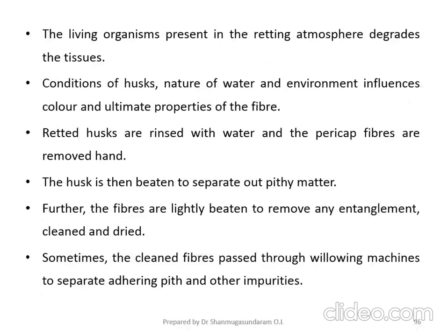So the living organisms present in the retting atmosphere degrade the tissues. The conditions of the husk, the nature of the water and the environment influence the color and ultimate property of the fiber. So during the retting process, you have to keep in mind the nature of the water and the environment, which will influence the color and ultimate property of the fiber. The water should be clean. If you use polluted water for the retting process, ultimately the quality of the fiber will deteriorate. So that is the reason why I have mentioned the nature of the water is very, very important during the retting process. Retted husks are rinsed well with water and pericarp fibers are removed by hand.